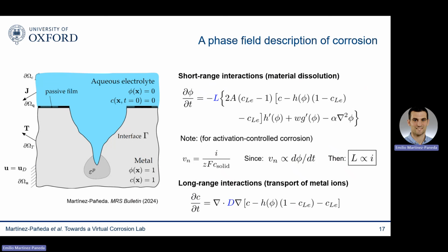But basically, at the end of the day, what you end up with is two equations. One for the short-range interactions, that is corrosion, material dissolution, which is what you see here. And this is basically the phase field equation, an Allen-Cahn type of equation. And then a second equation to describe the transport of the metal ions, which is a diffusion type equation. I will not give details on the numerical implementation, but it is straightforward in any finite element code. And we openly share all our code so you can see it all there.